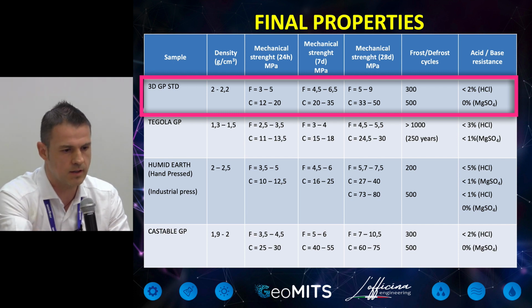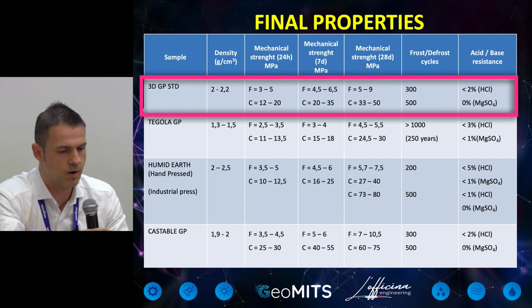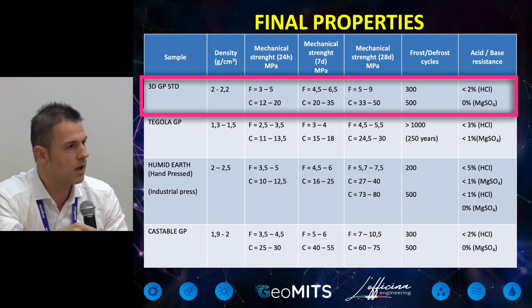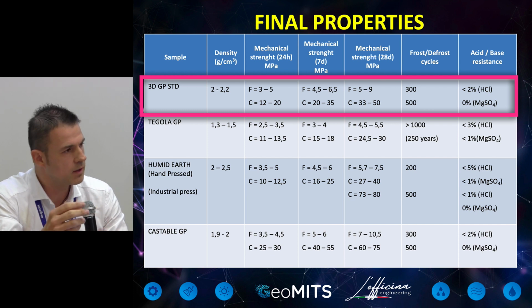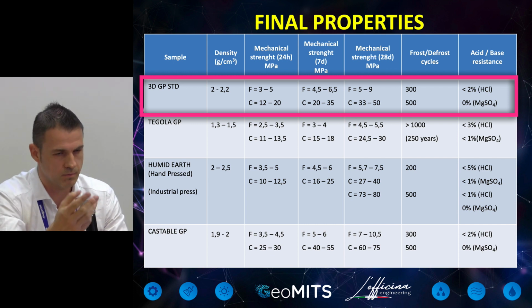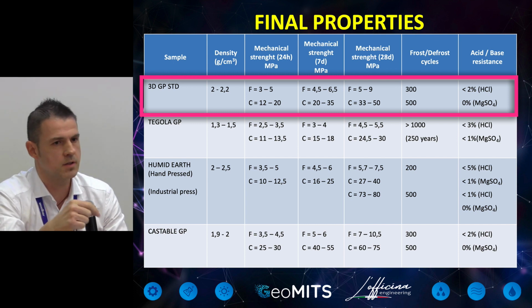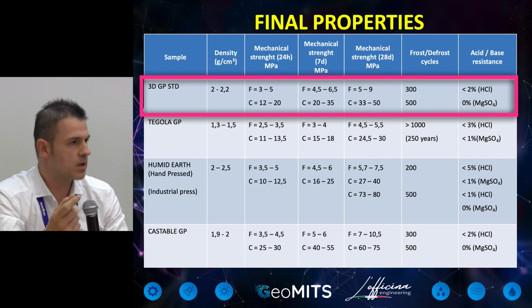And so you can see that after 24 hours, you have from 3 to 5 about flexural, and from 12 to 20 about compressive. And to arrive at 28 days, so with a compressive strength between 33 to 50. And this is a normal result. It's possible to do better. I obtained also 90, changing the aggregate. I have brought with me some little pieces using zircon waste. And with zircon waste, you can arrive at 90 without any problem.